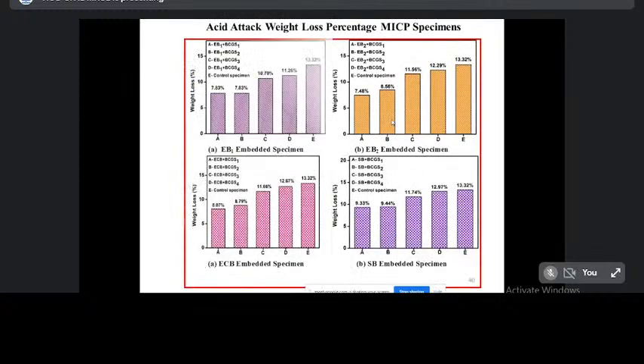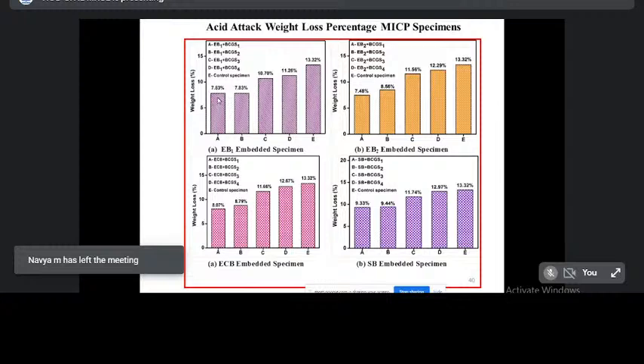This is the weight loss percentage of MICP specimens. The first one, the EB1+BCG1 embedded cement mortar specimen, shows 7.83%, but the control specimen shows 13.32% weight loss. As compared to control, the bacterial embedded cement mortar specimens show less weight loss. Likewise, the EB2 embedded, ECB embedded and Serratia embedded cement mortar specimens' weight loss is shown in this figure.